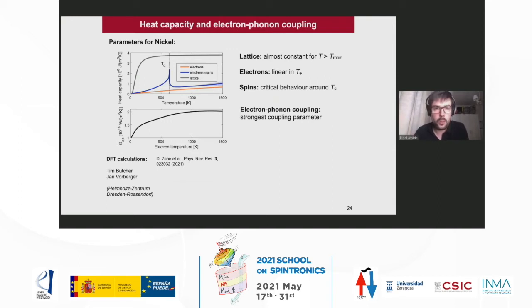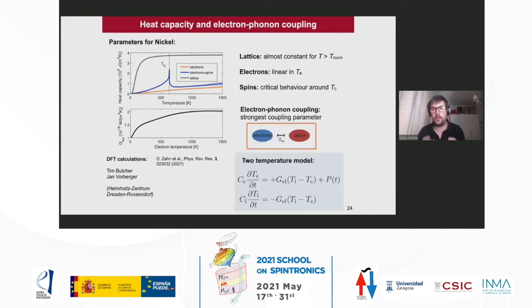So what we did was investigate this three temperature model starting from the simplest case: we assumed a two temperature model. We know the specific heat of the electrons, the specific heat of the lattice, and the electron-phonon coupling from DFT calculations. We know the laser pulse, the energy we put into the system, so we have no fitting parameters.